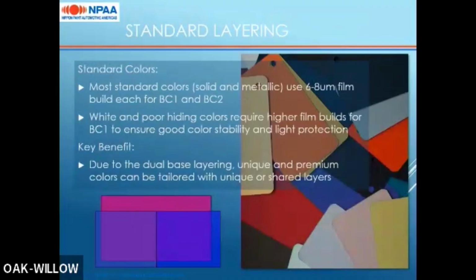Just as an example of some standard layering, for most standard colors, so not your premium colors, not whites, they use a film build of 6 to 8 microns for each base coat layer, with white and poor hiding colors typically being higher than that. For example, one of the whites that we have developed in this technology uses a base coat 1 film build of about 32 microns. So that kind of doesn't help with the thin film portion, but because of the consolidated application process, there's still a lot of cost benefit to that. But all of them are designed to optimize the light protection.